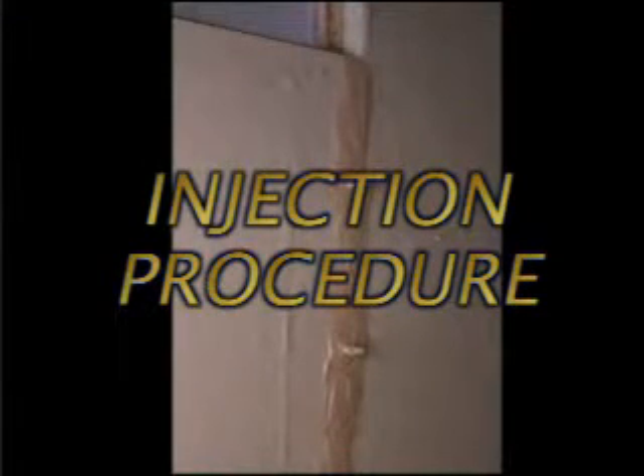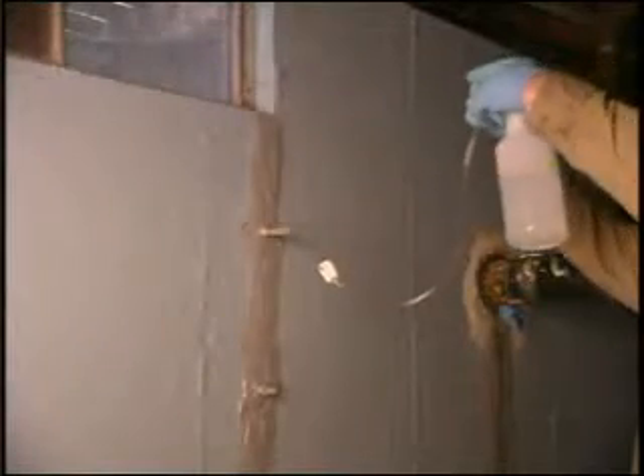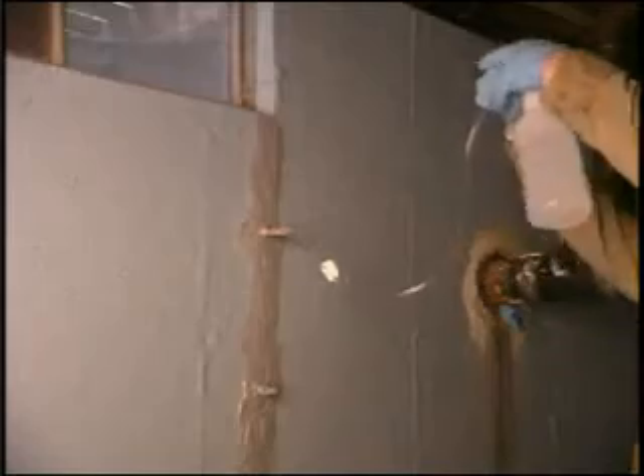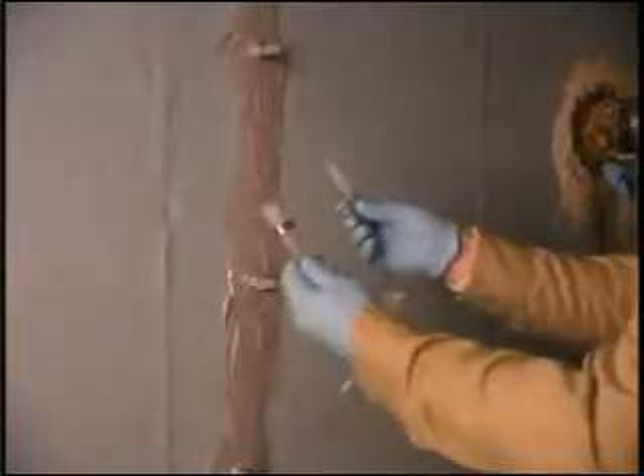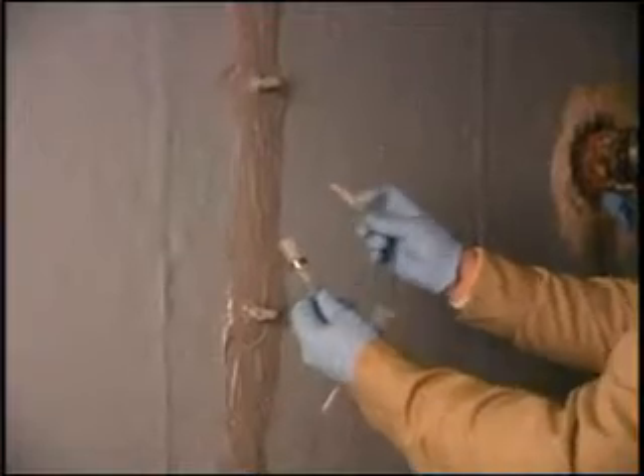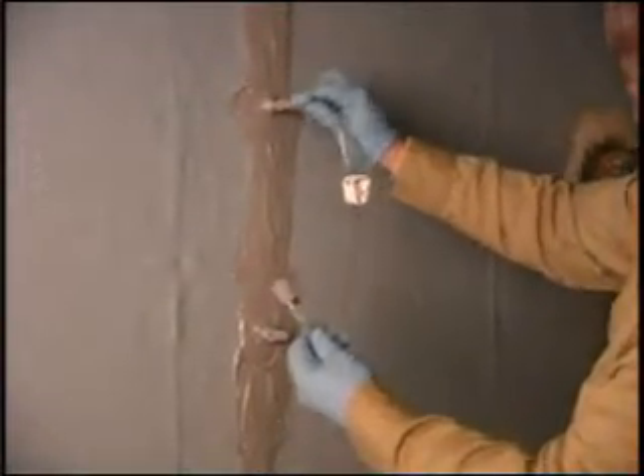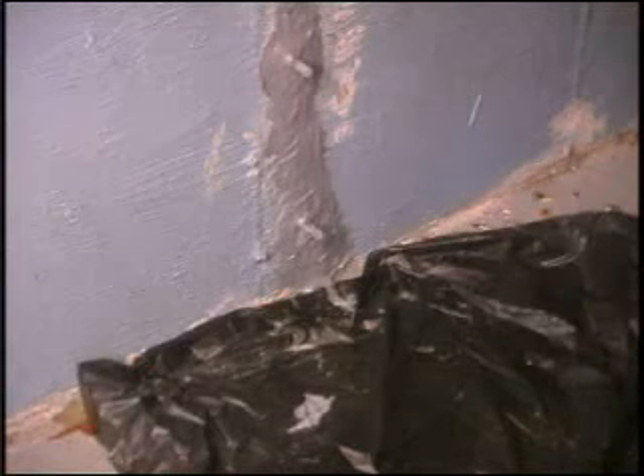The procedure for injection is as follows. Number 1. Flush the crack with 1 to 2 cups of water poured into the top port using plastic squeeze bottle or by filling the hose assembly several times. Water should come out of every port below the top port, indicating that the crack is contiguous and that ports are not blocked by epoxy.